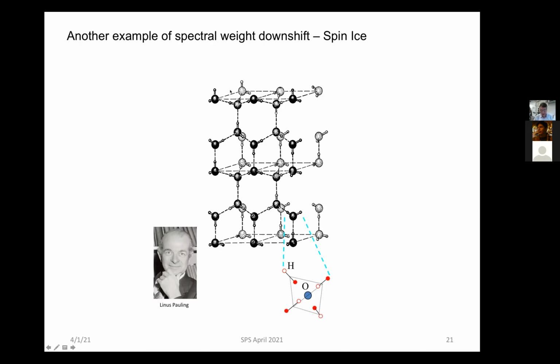So it turns out that there was a problem in the 1930s. There were groups who had measured the configurational entropy of water at room temperature. And they did this by measuring extremely accurately the rotational and vibrational modes of the water molecule using infrared spectroscopy. And then there was another group who measured the entropy at room temperature by integrating the specific heat from helium temperatures all the way up to room temperature. What really impresses me is the accuracy of these measurements back in the day. And what they found was a discrepancy.